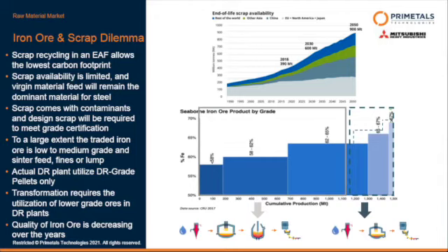On the other hand, and that's the figure at the bottom, if we want to go for direct reduction and we see the raw material that is utilized today in direct reduction, it's only the DR-grade iron ores, the high quality iron ores, at least 65% iron, more likely 67% iron ore. But the large share that is traded, so this iron ore is much lower quality.